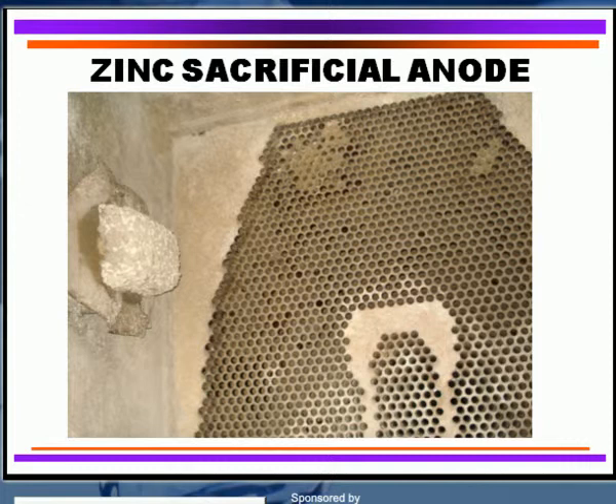Many people also use magnesium, and the magnesium, of course, does provide protection to your equipment, but it is a very effective technique to use. Do not use aluminum. Aluminum is probably the worst thing you can use for sacrificial anodes because it produces a lot of deposits of aluminum. It reacts with phosphate to cause severe depositing in the tubes themselves, so don't use aluminum. Use either zinc or magnesium.